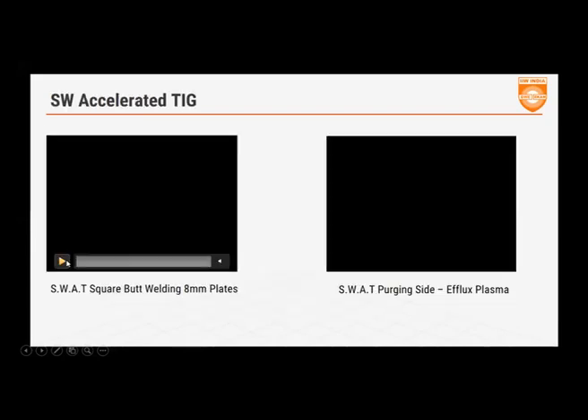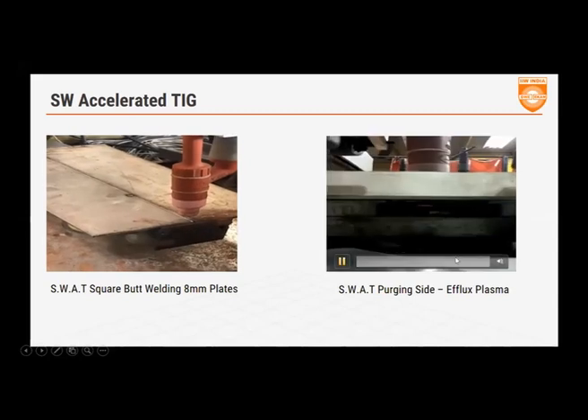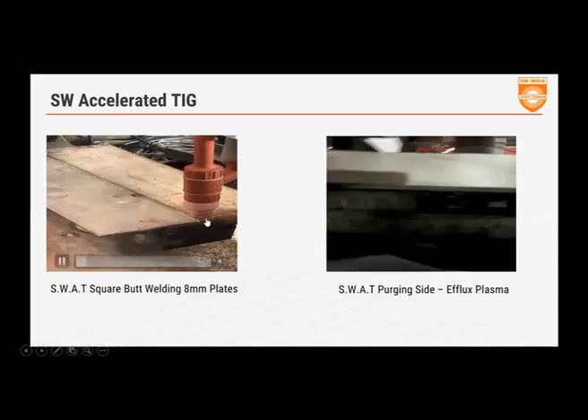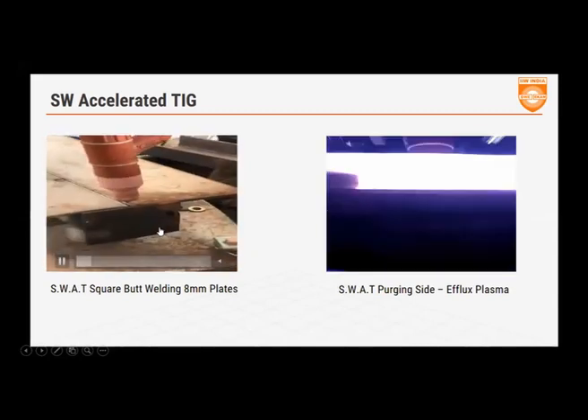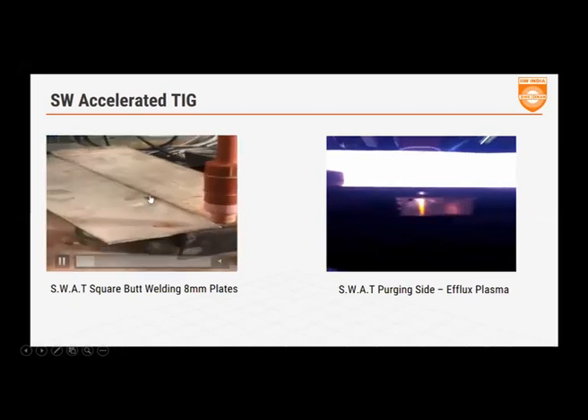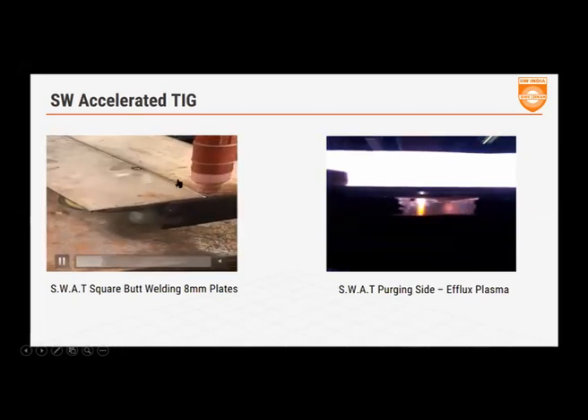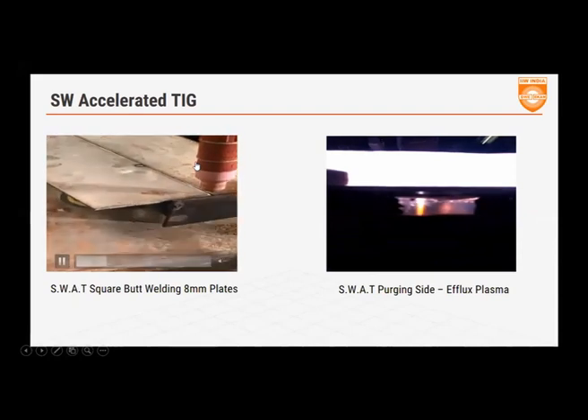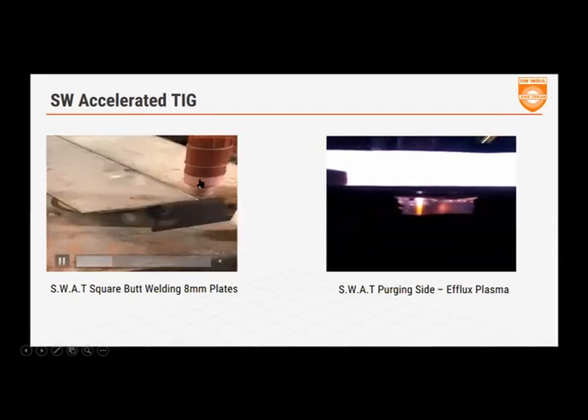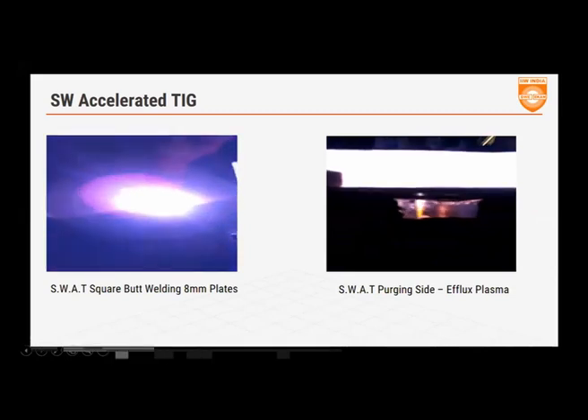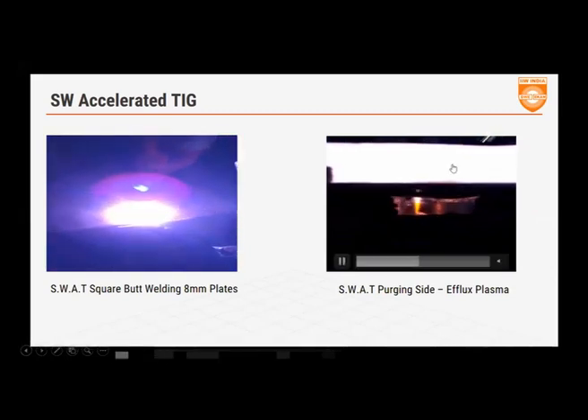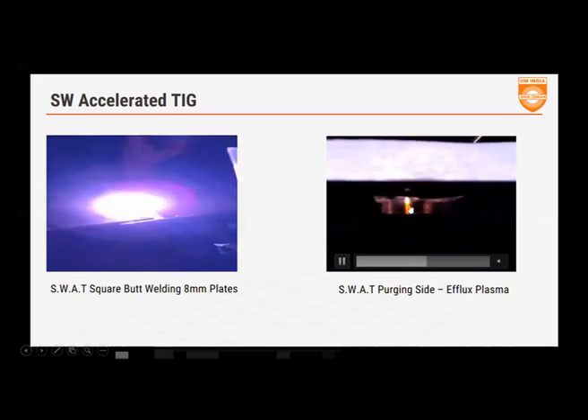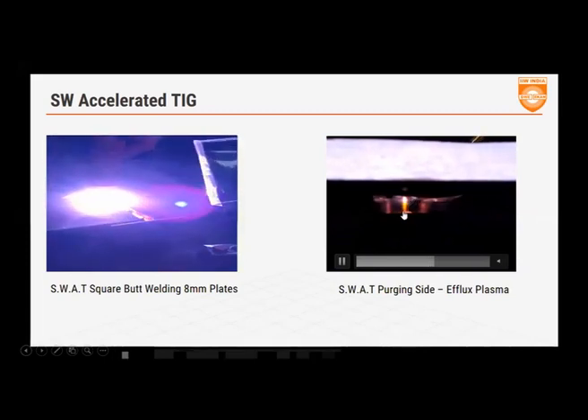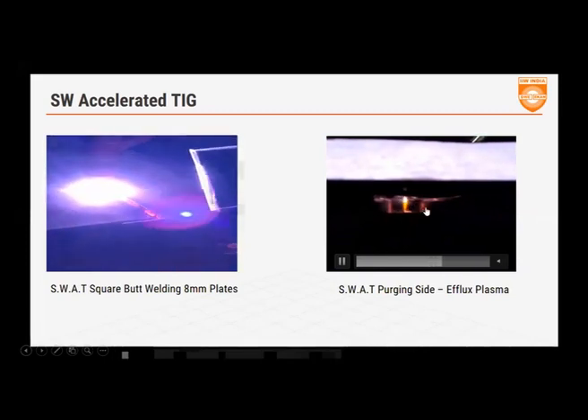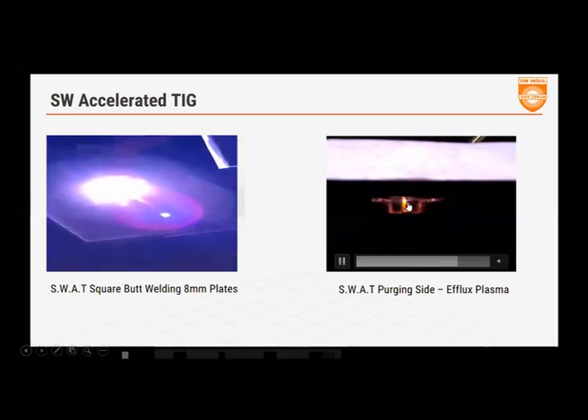So can I show you quick videos? If you can see here, this is a typical 8 millimeter thick stainless steel plate. You can see no edge preparation is done. Simply put on top, the torch is mounted on a simple column boom. We'll get the boom to move at about 400 millimeters a minute. On the other end, if you see this video here, what is happening on the other side: you can see the efflux plasma exiting. You see all the gases coming out. The consistency of this plasma tells you that there's a very even penetration happening all across.